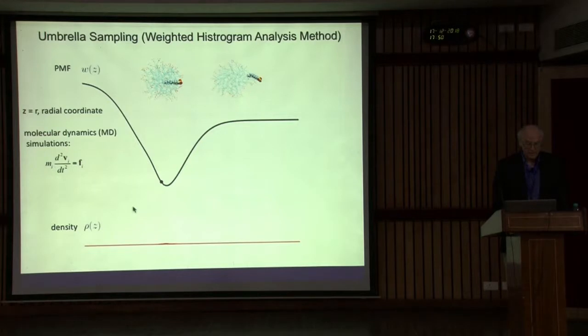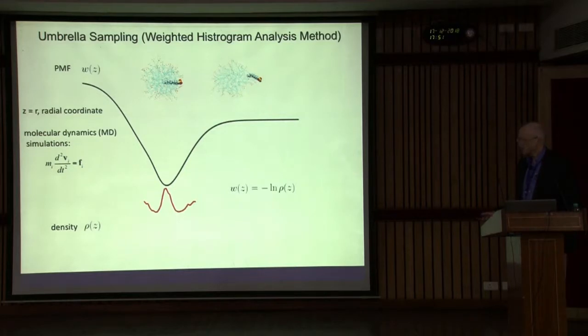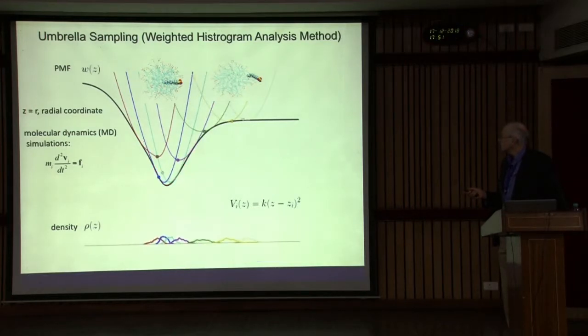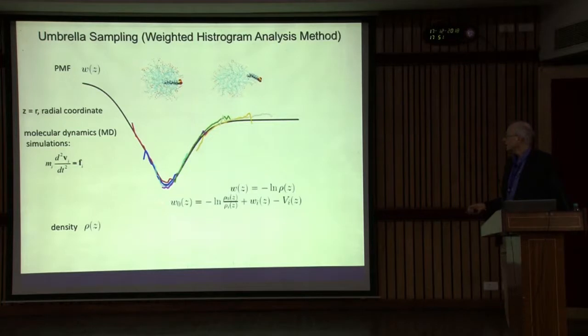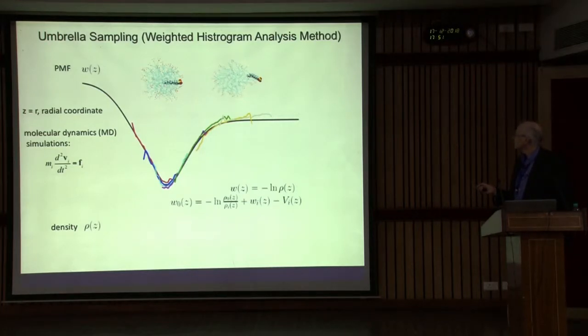If you track the center of mass of the surfactant molecule relative to the center of mass of the micelle, what you'll see is the surfactant rattles around in the bottom of the well. You can collect the statistics of that and form a histogram, which is related to the shape of this well through the Boltzmann principle — the logarithm of that histogram tells you the shape of the potential well, but only at the bottom. To determine the shape elsewhere, this method involves creating bias potentials — harmonic potentials located wherever we want — running simultaneous simulations, collecting histograms, taking logarithms, and subtracting off the biasing potential.